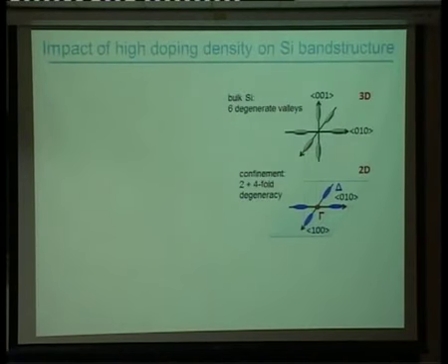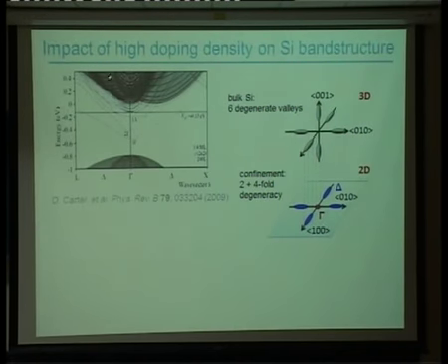So what does this abrupt doping do? Now, Shankar talked before about our 6 bulk degenerate valleys in silicon. When we have this very abrupt doping in the vertical direction, we basically break those valley degeneracies. So we end up with 2 valleys out of the plane and 4 valleys in the plane. And because we have essentially this very high doping, what we find is we get an impurity band that comes down below the Fermi energy.